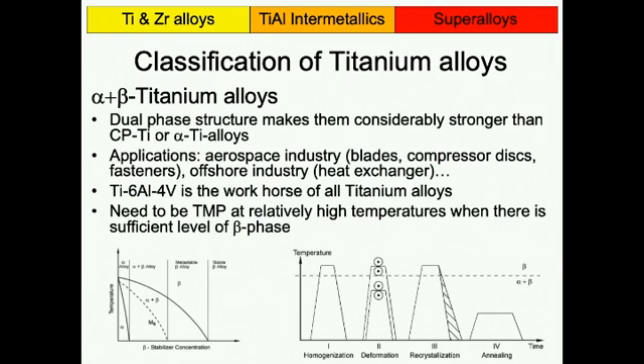And then we get to the alpha plus beta titanium alloys. These are now the dual phase titanium alloys. I've already mentioned it. Well, they essentially have beta phase now also at room temperature, and not just in tiny pockets to mop up the hydrogen, but you really have noticeable or detectable beta phase in that alloy at room temperature. And because it's a dual phase structure, they are actually inherently stronger than single phase alloys. So they're stronger than CP titanium, and typically stronger also than alpha titanium alloys.